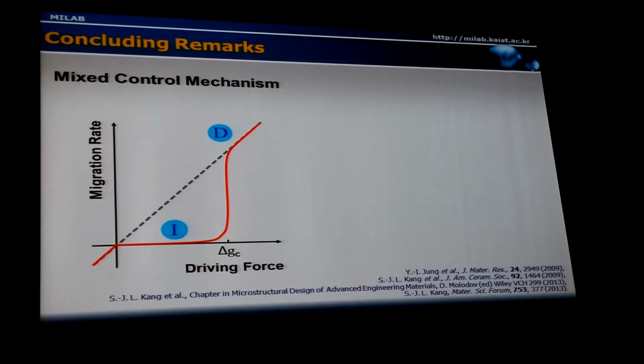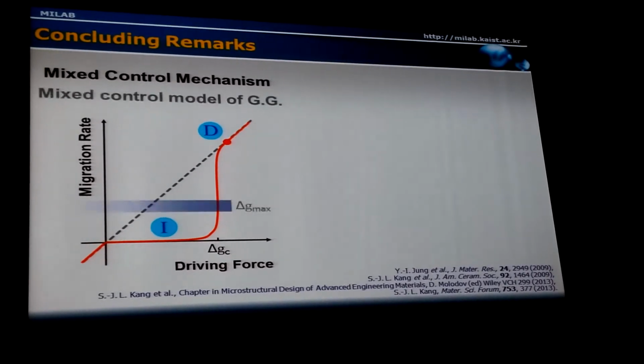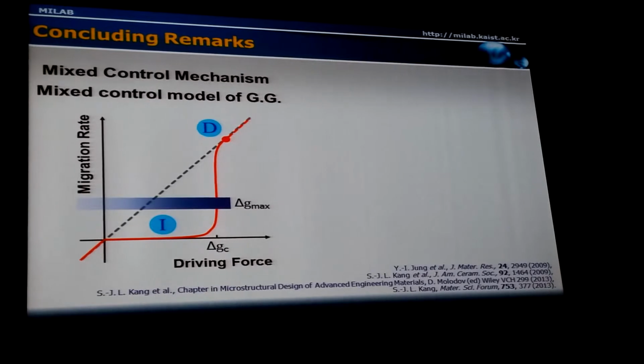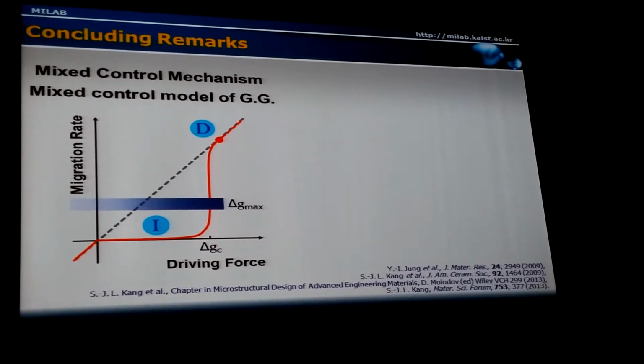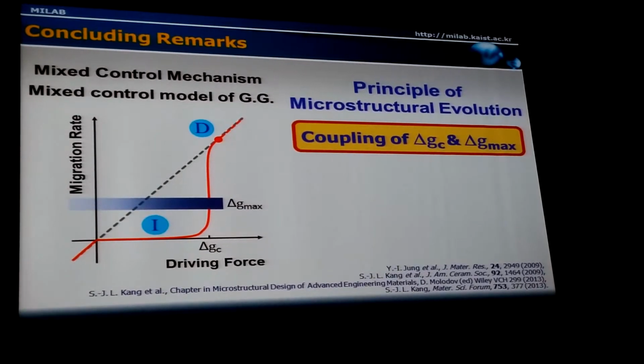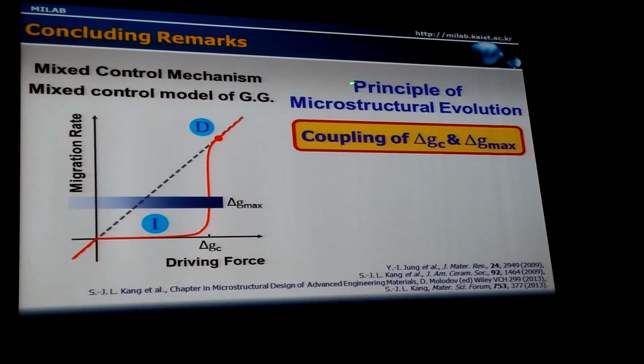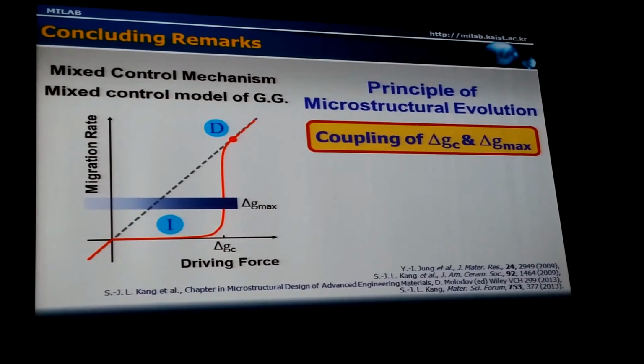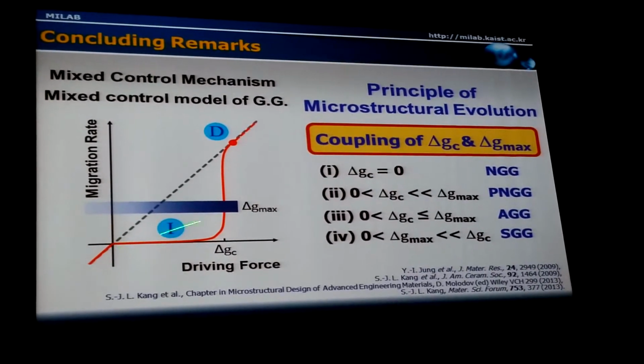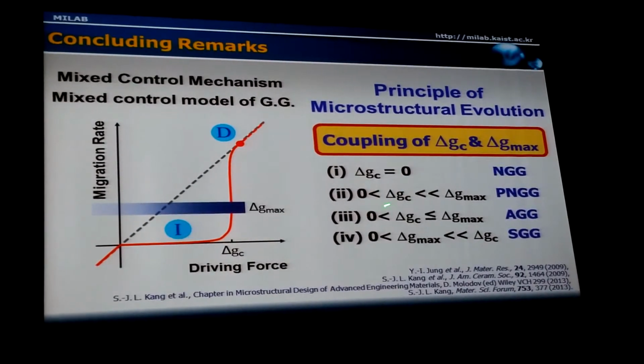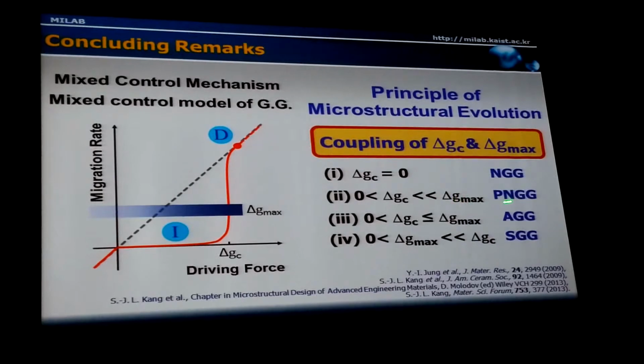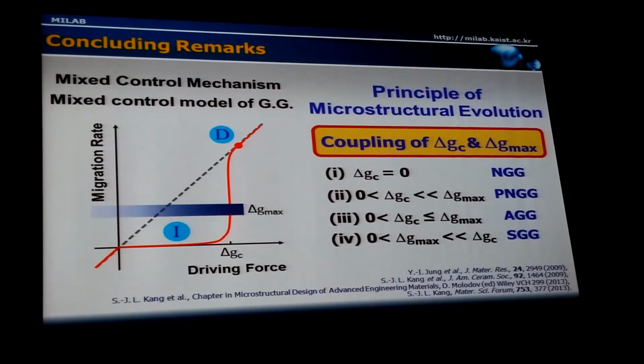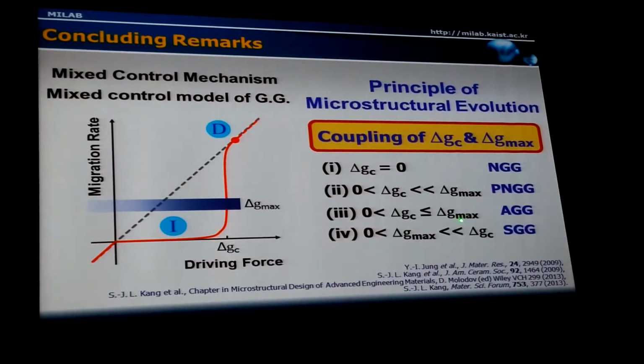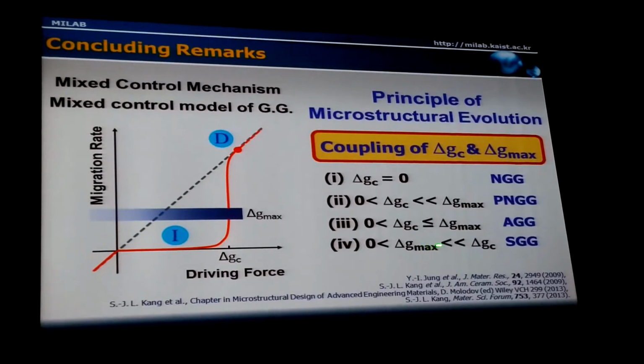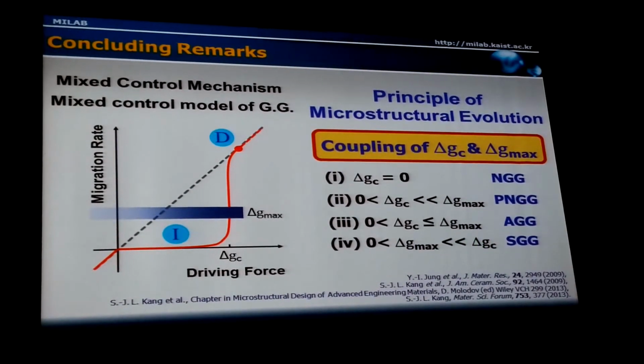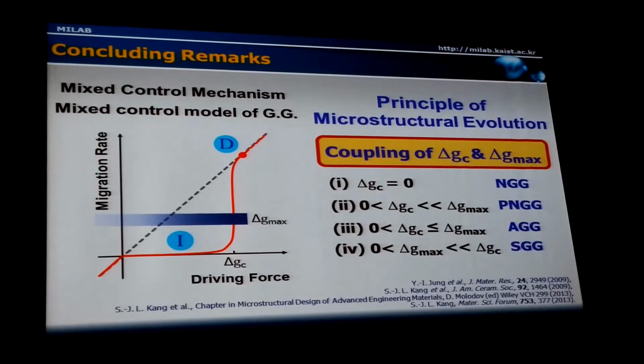So we developed a mixed control model in boundary migration, and then we added the grain growth behavior there. We proposed the mixed control model of grain growth. From this, we can deduce the principle of microstructural evolution, which is a result of the coupling effect of the critical driving force and the maximum driving force. When the critical driving force is 0, then of course normal grain growth occurs. When the critical driving force is non-zero but much smaller than the maximum value, the growth behavior is still quite normal. When the critical driving force is comparable with the maximum driving force, abnormal grain growth will result. And when the maximum driving force is much smaller than the critical value, there is no grain growth, stagnant grain growth.